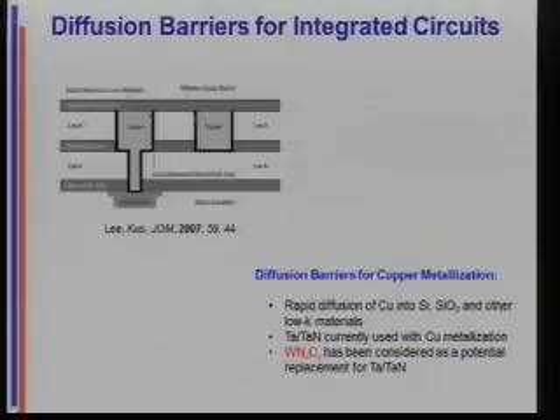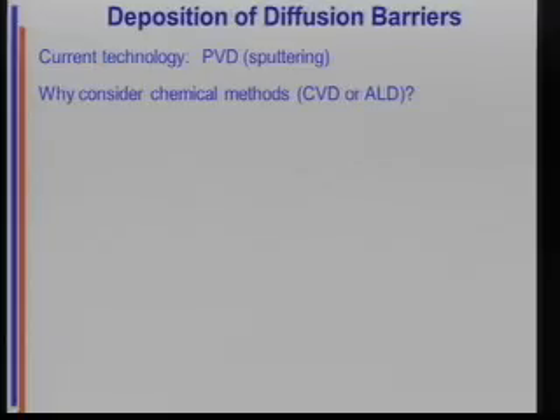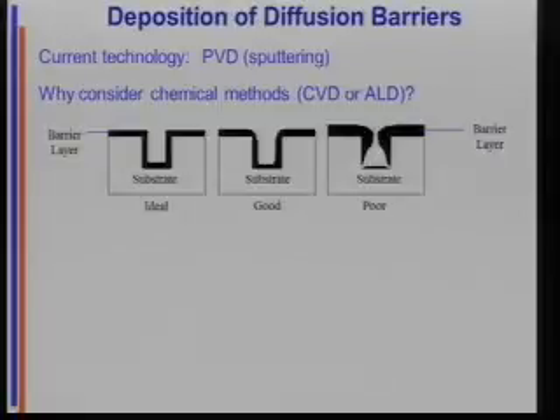And so at the time, tungsten nitride and the tungsten nitride carbide ternary material were basically one of the best candidates for the switch to copper metallization. They're going to use those as diffusion barrier material. Okay. And so the technology that was used then and is still used now is physical vapor deposition or sputtering. But there's a problem with sputtering. And that problem has to do with conformal coverage of features on a chip.